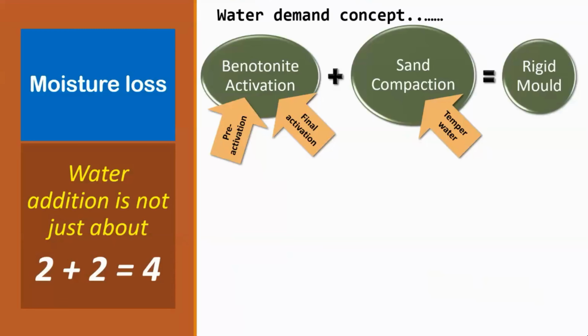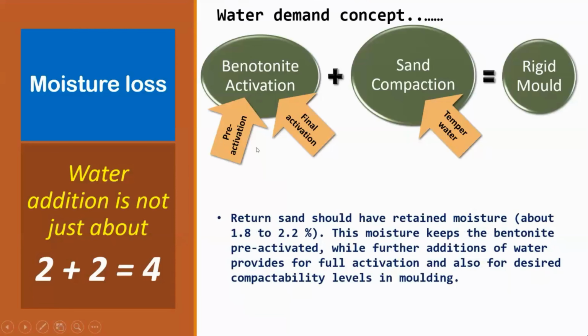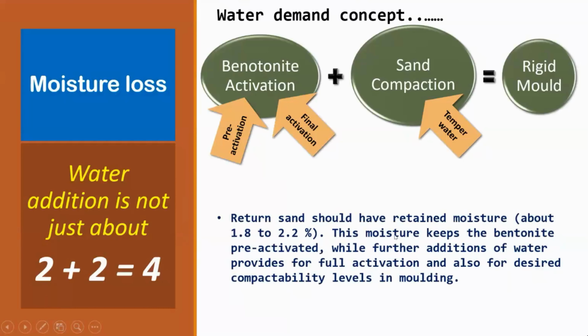Otherwise, you will have to add a lot of water inside the mixer and then wait for all of the water to get absorbed. This activation of bentonite is not instantaneous, it takes some time. So always pre-activation is going to help in activating the bentonite before it reaches the mixer. And the final activation can be done inside the mixer during the mixing cycle. So the return sand should have retained moisture. This is pre-activation, about 1.8 to 2.2%. This moisture keeps the bentonite pre-activated, while further additions of water provides for full activation and also for the desired compactability levels in mold. It is a temper water. So here the word compactability is introduced.